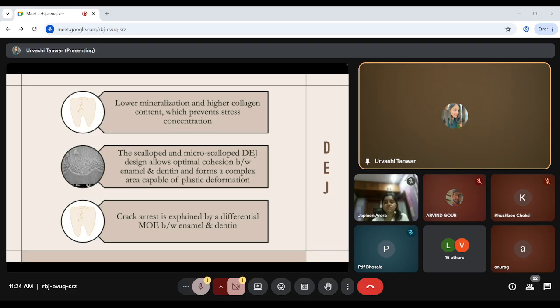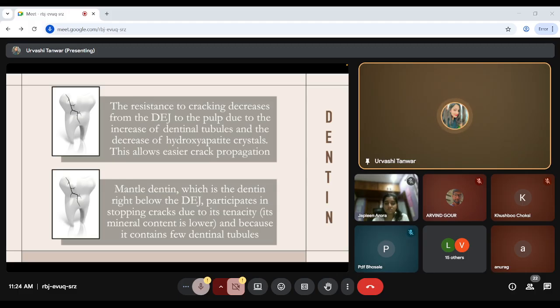Crack arrest is explained by a differential modulus of elasticity between enamel and dentine. But when you come to dentine itself, the resistance to cracking decreases from the DEJ to the pulp because of the increase in the dentinal tubules and the decrease of hydroxyapatite crystals. And this allows for easier crack propagation, which is why whenever you have cracks in the dentine, they need to be removed because they will propagate and they will propagate in a very fast manner.